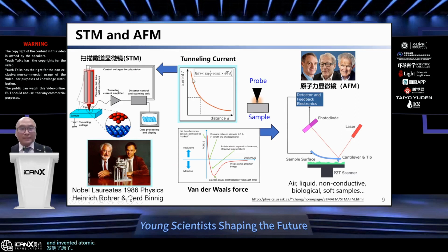So they replaced the distance and the current with the van der Waals force with the distance. So they can maintain the distance with the same, so the force is the same. In order to measure the force, they use a laser to shoot at the back of the micro cantilever, and use the laser spot to reflect the spot movement to get the displacement or deflection of the micro cantilever. So this technology greatly expands the application scenario for air, for liquid, and for non-conductive, even biological samples.